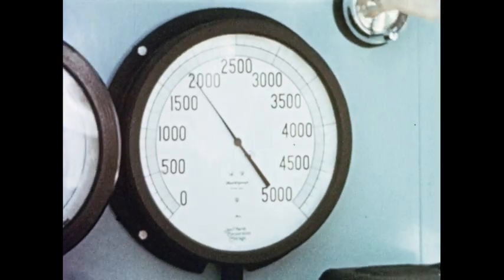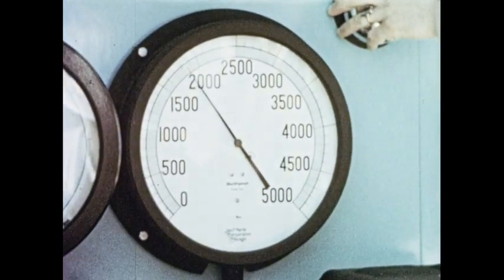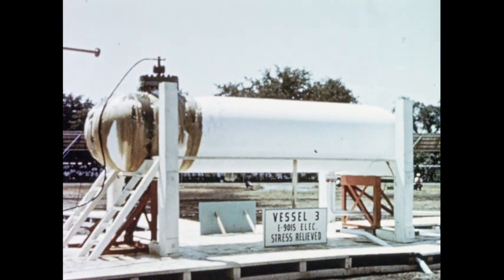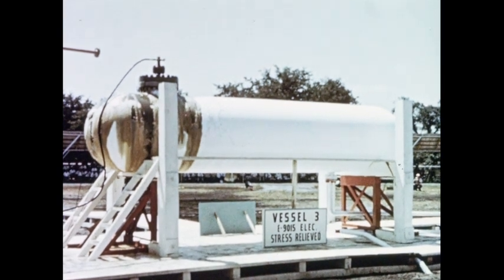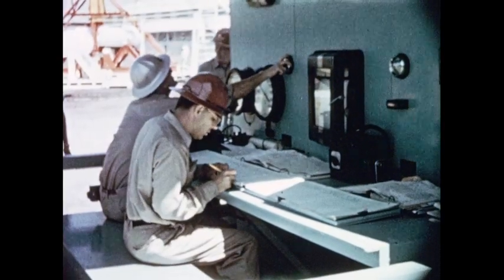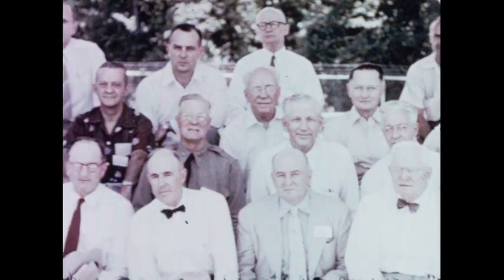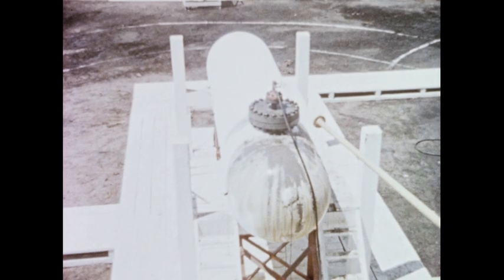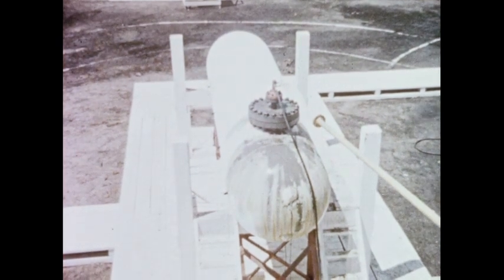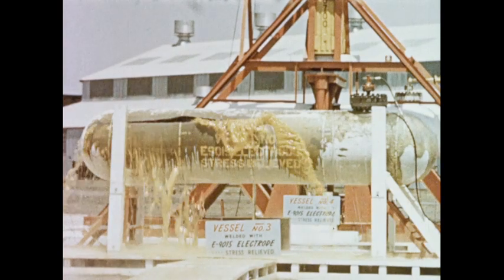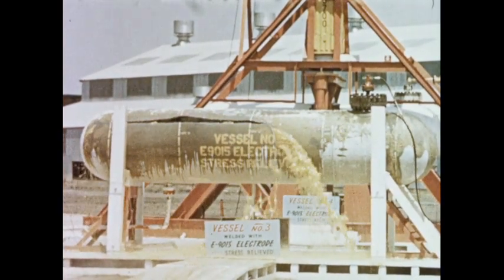When pressure reached 1875 psi, T1 already showed 3 times the yield strength of ordinary steel. But how extraordinary was it? It held at 2,000 pounds. It passed 2,500. Finally, at 2,850 psi, the vessel burst at a pressure 7.5 times the maximum now required for equipment of this kind.